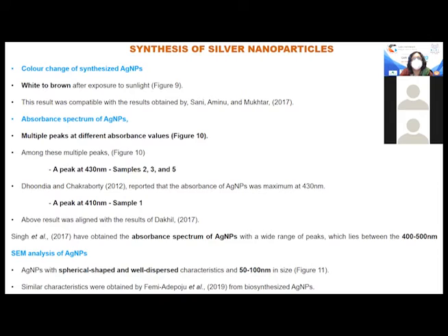So we got multiple peaks at different absorbance values. For samples 2, 3, and 5, we got a peak at 430, and for sample 1, we got a peak at 410. All these values are equal to previous research studies. Also, Singh et al., 2017 obtained an absorption spectrum of silver nanoparticles with a wide range of peaks, which lies between 400 to 500. So that is the range of silver nanoparticles.